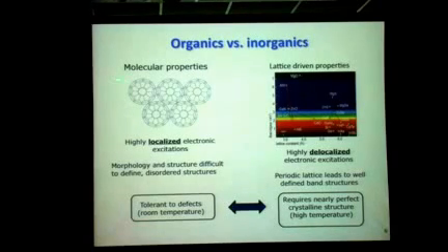That really comes from the fact that you're fabricating these films at a relatively low temperature, so there's a lot of disorder. As a result, the electronic excitations are actually quite localized, as opposed to inorganic perfect crystals, where you have much larger delocalization.